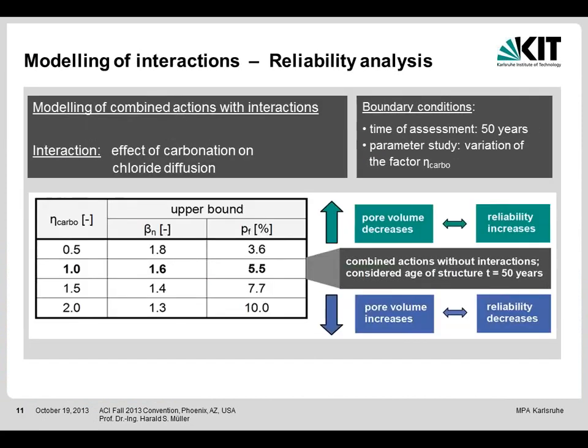And these interactions, which I mentioned for chlorides and carbonation, are also very sensitive and have to be looked into in detail. If we look, for example, at a time of assessment of 50 years, and we include for the diffusion coefficient a combination factor, eta carbo, and we set it to 1.0, then we have no interaction, we have our design age of 50 years without any interaction. The limit is a safety factor of about 1.6.